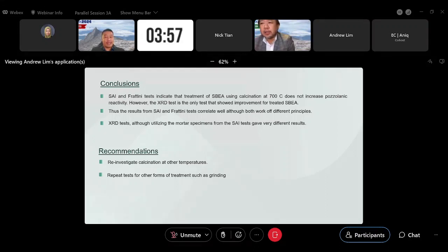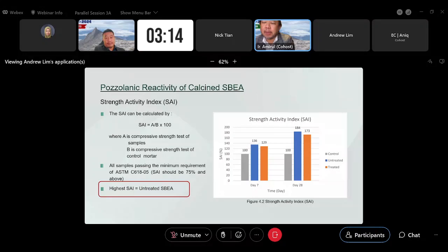Anyway, perhaps you can share with us the ratio of your SBEA composition in any of this concrete mix, whether that has any significant variation to the outcome of your result, especially in regard of the reactivity between the SBEA and your treated mix. If I can see in your conclusion, as of now, this SBEA has actually improved the concrete strength substantially. So whether the mix can be adjusted in order for you to achieve the most optimum increase of the strength of the concrete.